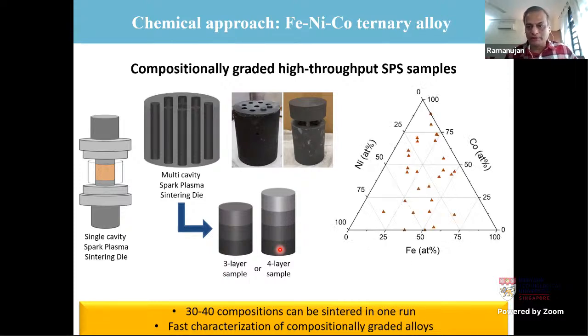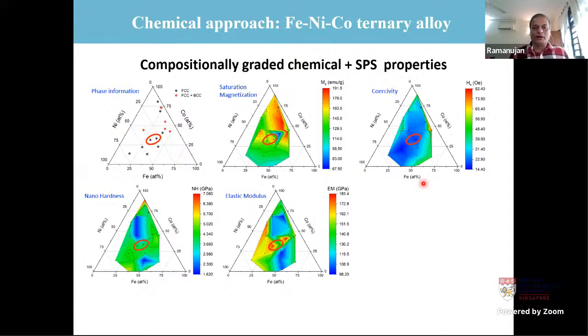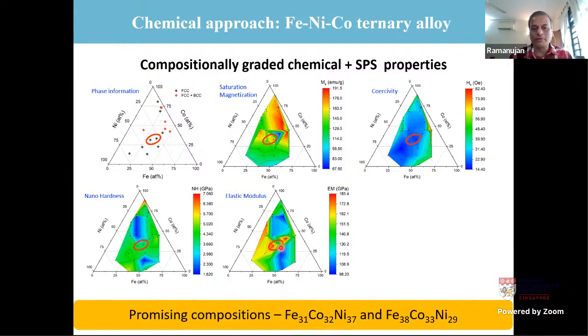Again, these are some of the compositions that we have looked at from this chemical perspective. And once we've done that, we measured the properties of these in this ternary space. So for example, we found out the crystal structure. We can find out the grain size as well. We found the saturation magnetization, coercivity, hardness values, elastic modulus. So we can identify these properties in the system, and we can identify certain promising compositions in this ternary space which have a good combination of properties. In this case, for example, these elliptical regions have a good combination of properties.